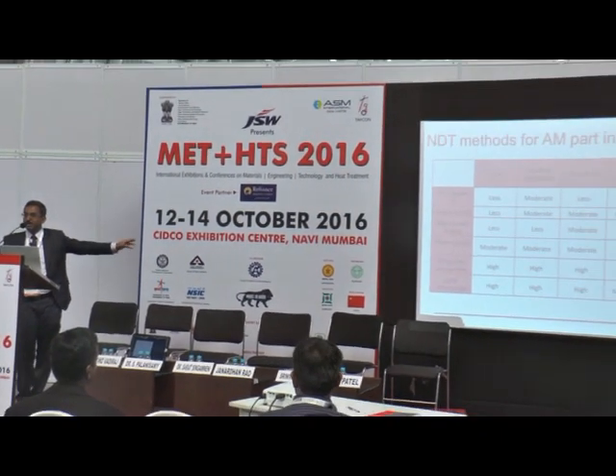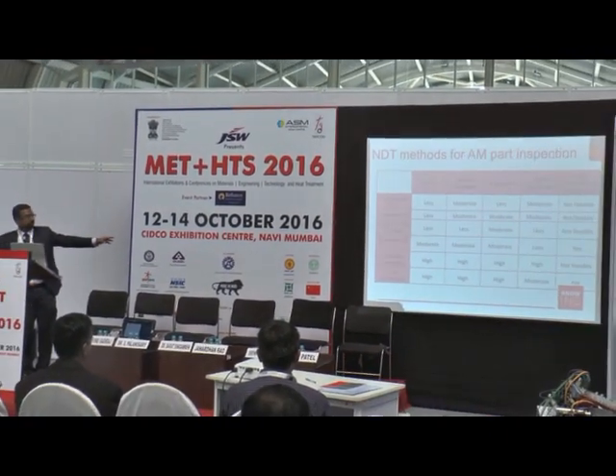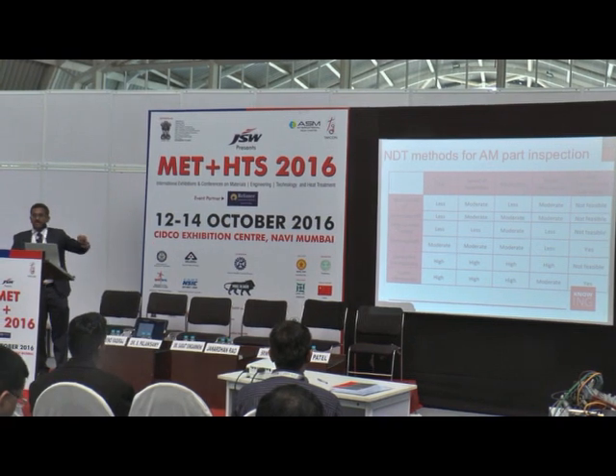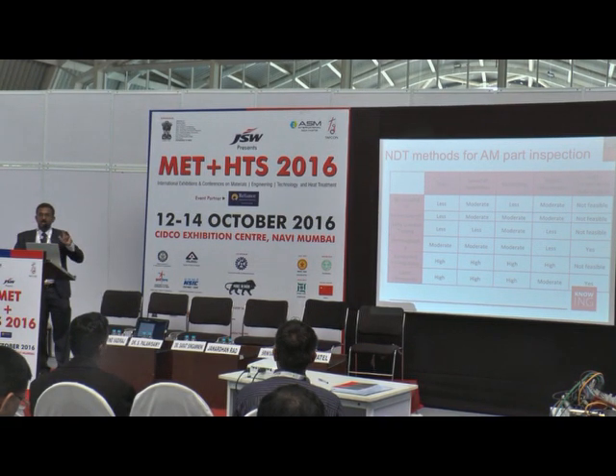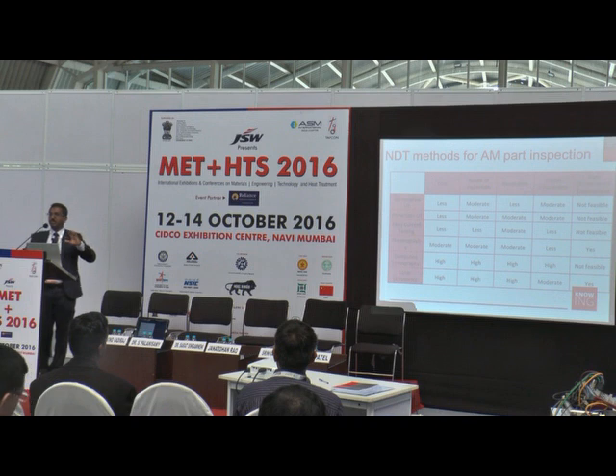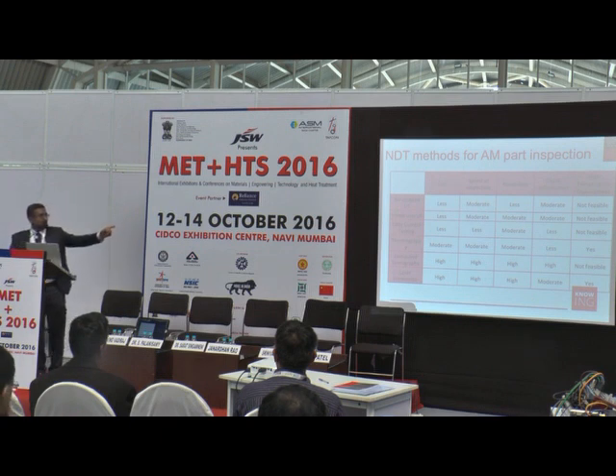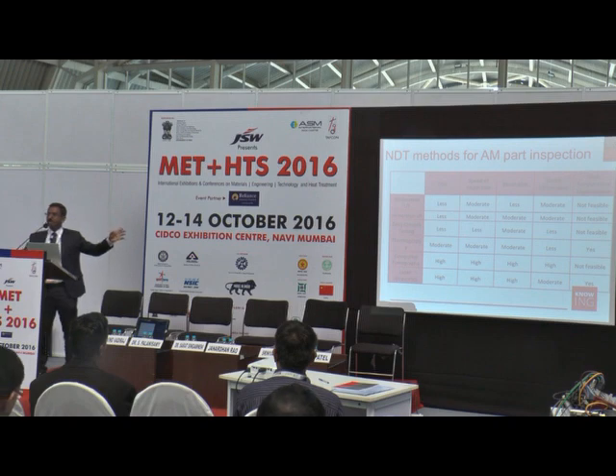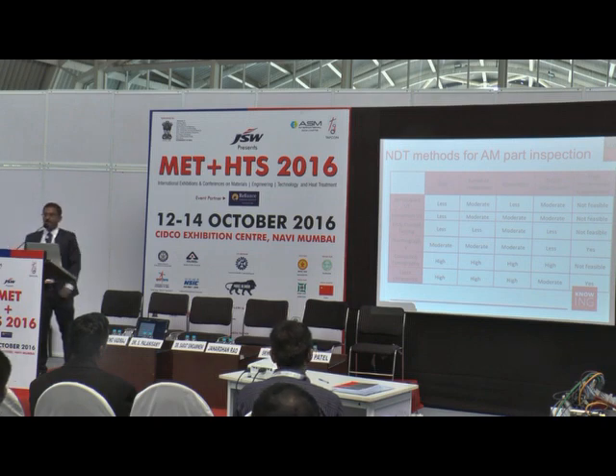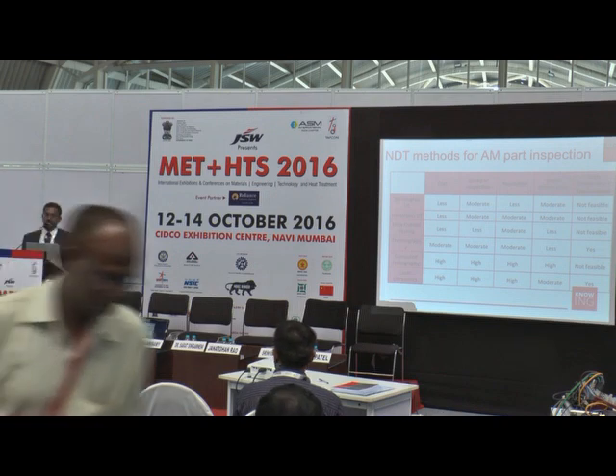Unfortunately, it cannot be used in high temperature conditions. However, in laser ultrasonics, you get a lot of information. Cost compared to tomography, it's cheaper. For example, if a tomography machine costs $1 million, a laser ultrasonic machine will cost you around $200,000, so it's 1/5 of the cost. The only problem is you may not get the information you get from tomography, but it can be applicable in high temperature applications. So when the part comes out at high temperature, especially with direct metal deposition, it can be used in that particular case.